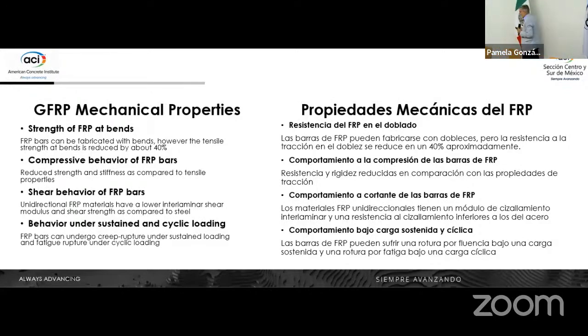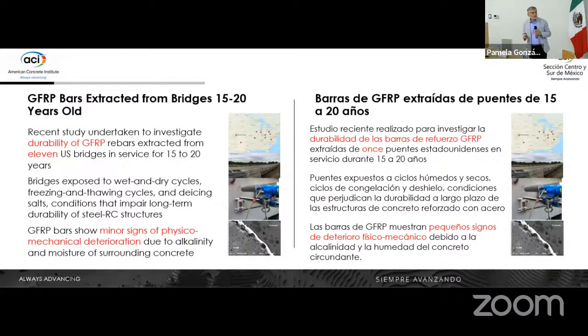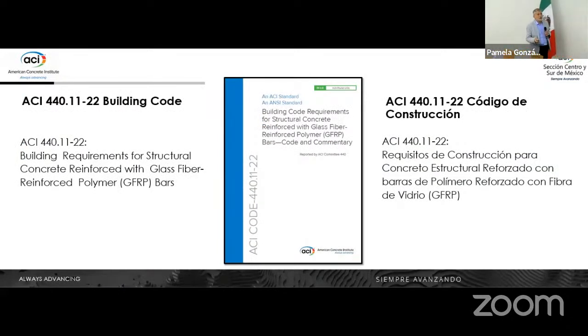What is the point that I'm trying to make? The point is nothing is perfect, but as engineers, we can design and we know what these properties mean to us. The other thing that we have done over the years, because there was a question about durability, is run tests on samples that came from bridges that had been in place for at least 15 years. And we have demonstrated that there is really no degradation of the GFRP bars, even though in those days the fibers were E-type, not ECR, and in many cases they did not use a vinyl ester, they used a polyester, which we no longer use. So this is the code. It's a great document. I hope that you will eventually put your hands on it.